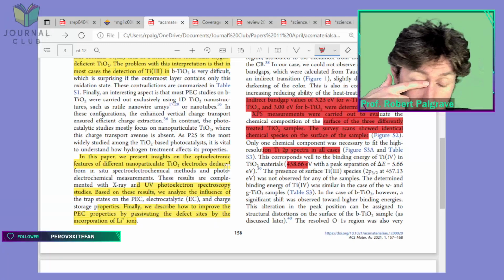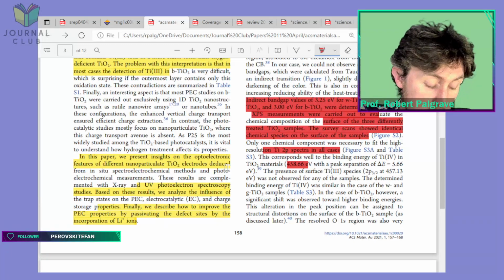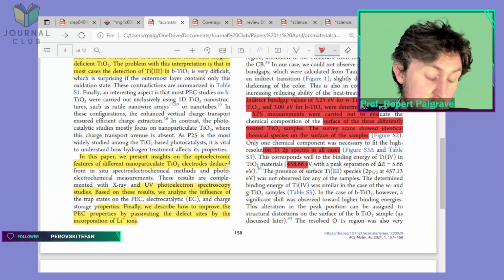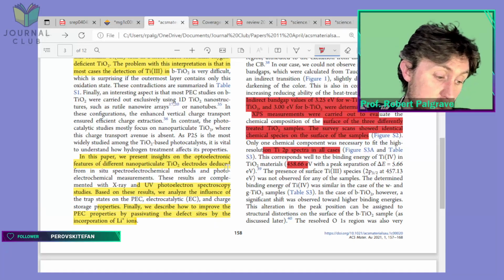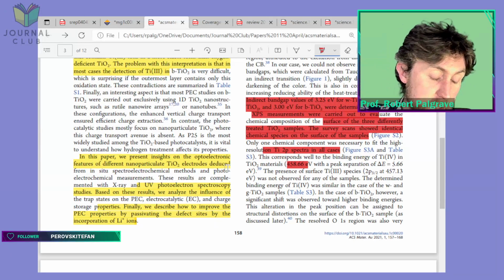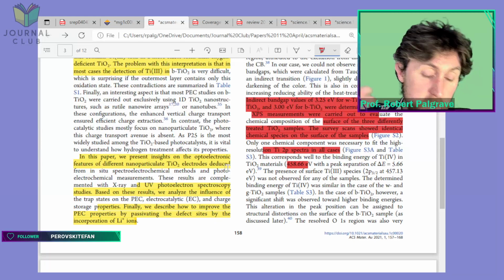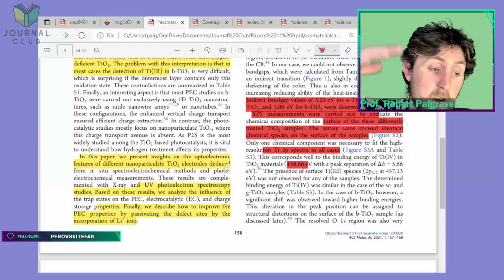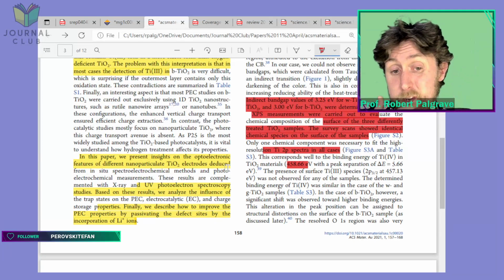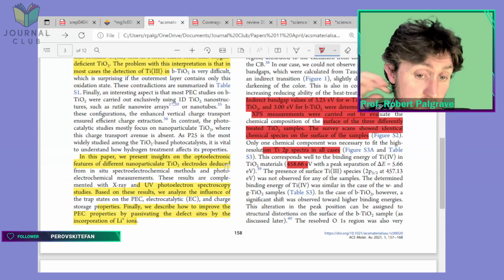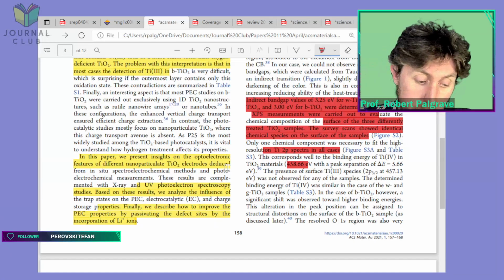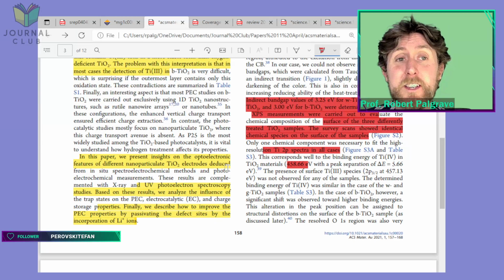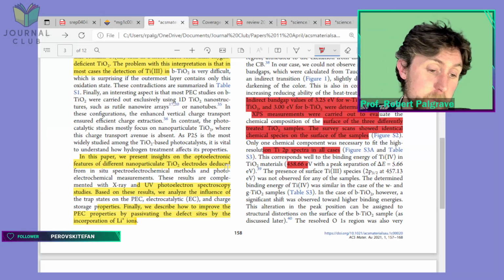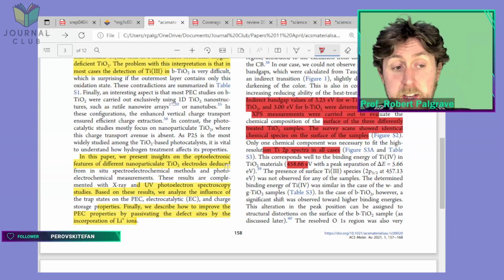So doping, if you're doping electrons or doping holes, so if you change the carrier concentration, or change the electron richness of the material, rather than carrier concentration, is probably a better way to say it, you can either raise or lower the Fermi level in your material. So when you raise or lower the Fermi level, many people don't realize this, I should say, you move the peak positions in your XPS, because XPS, the binding energy scale, is referenced to